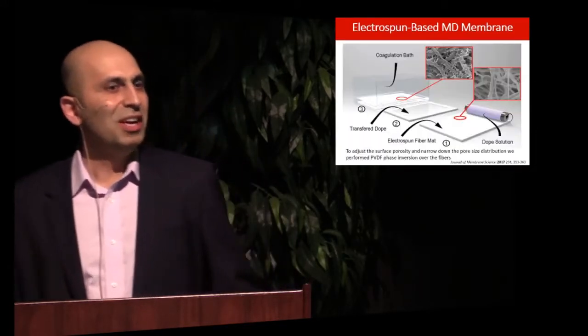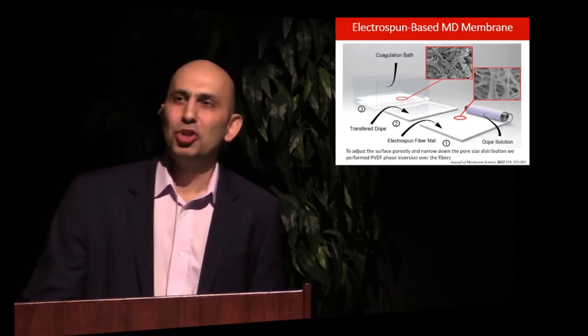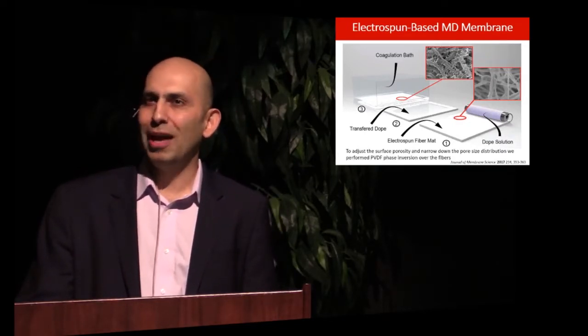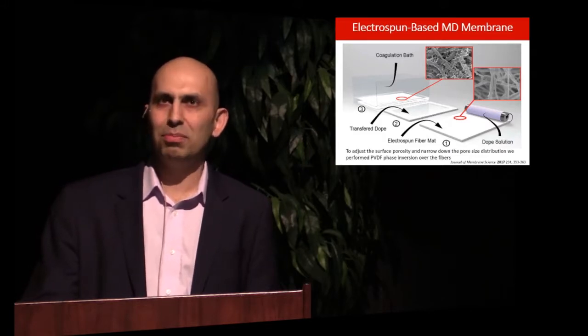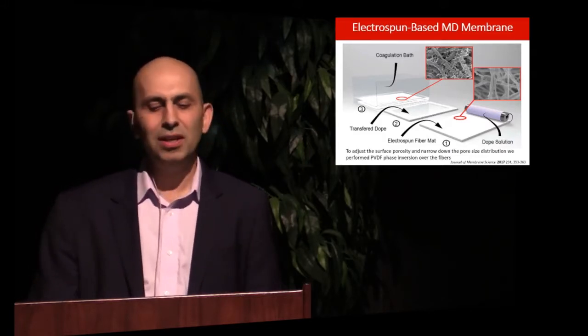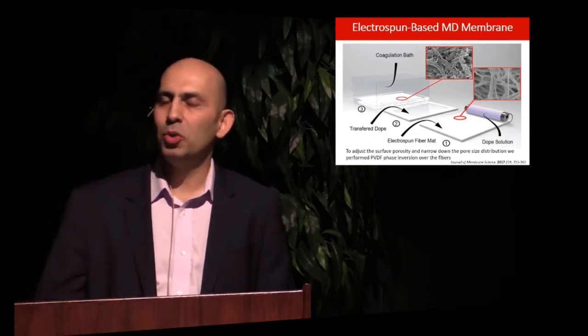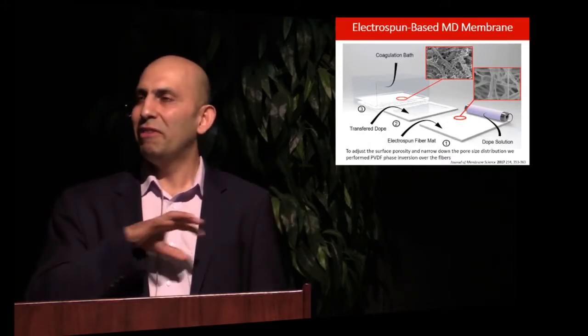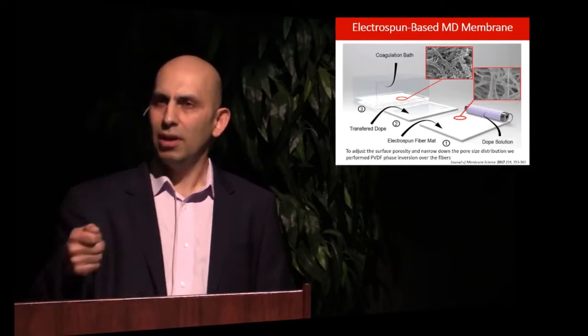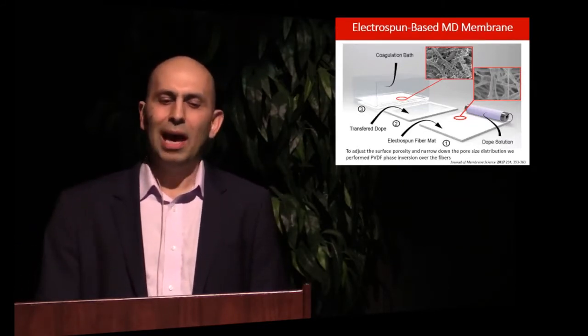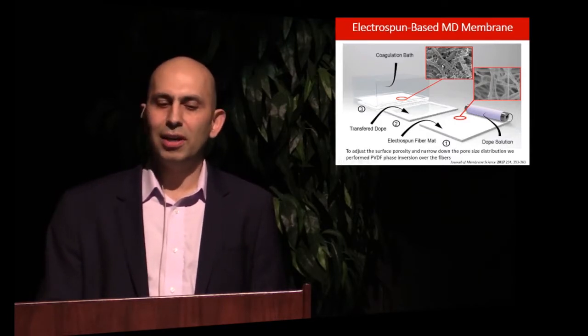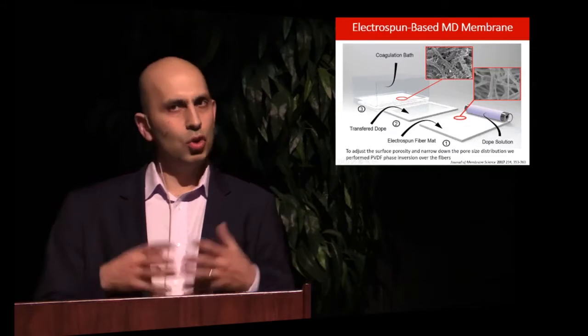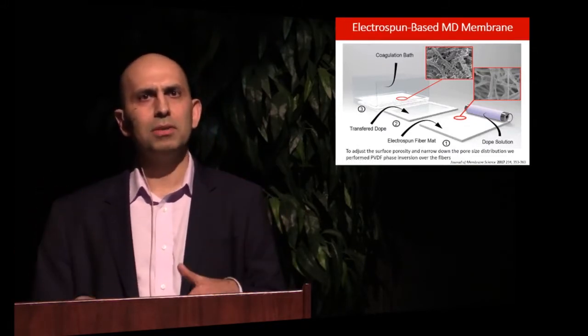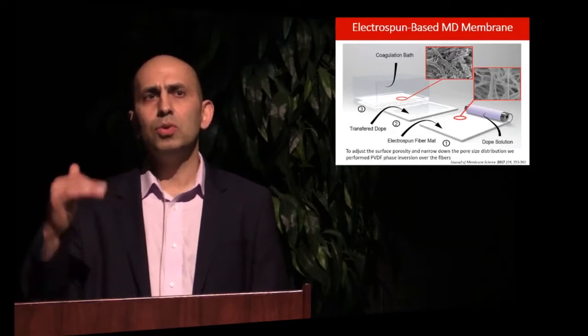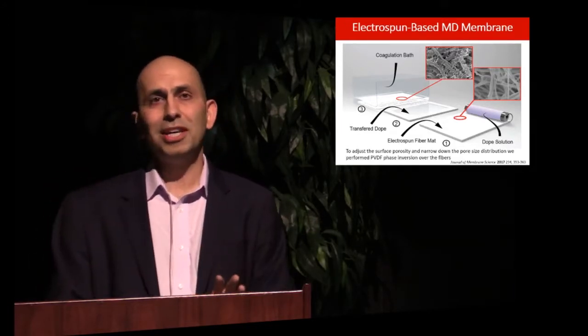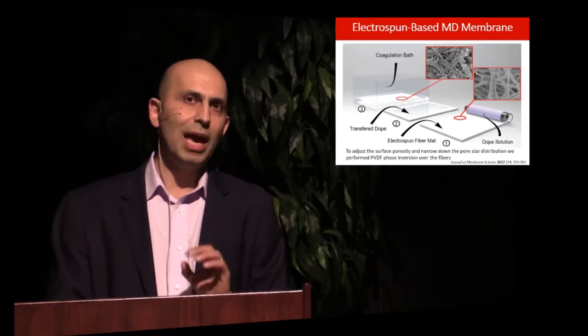We try to come up with the best possible solution-based process that we could apply to the top of this membrane to adjust the pore size. Here's what you see. We basically have something very similar to a painting brush. We wet that painting brush with a new polymeric solution, and we paint the top surface of that mat. What happens is that when you do the coagulation, you start getting a much denser structure. So you address the problem associated with meniscus breaking and water goes through, but as a result, you're losing the flux again. So we do realize there's a technology gap in material processing.